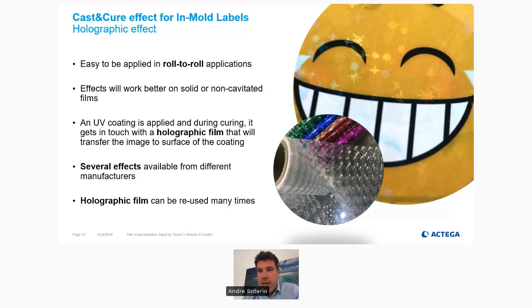So the cast and cure effect is easy to apply in roll-to-roll applications. The effect will work better on a solid or non-cavitated film. Here, a UV coating is applied, and during the curing, it gets in touch with a holographic film, like you can see here on the slide, and that will transfer the image to the surface of the coating, and you have a very nice holographic effect. There are several effects available from different manufacturers, and this holographic film can be reused many times. It's quite difficult to use in sheet offset applications, but quite easy in a roll-to-roll application.